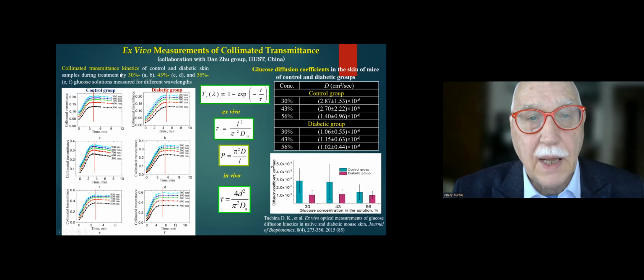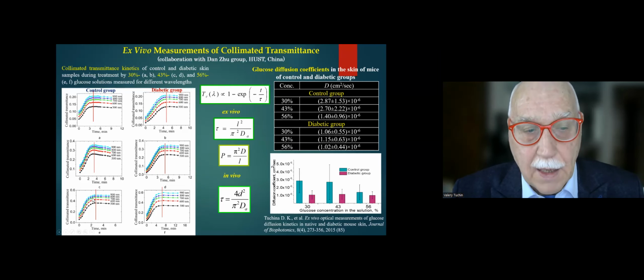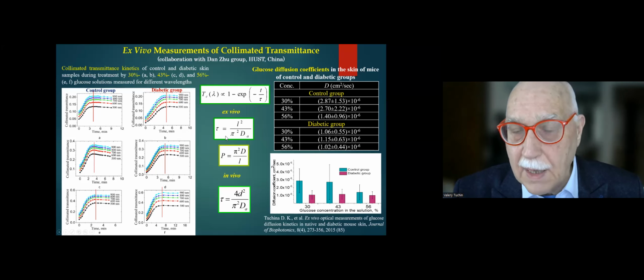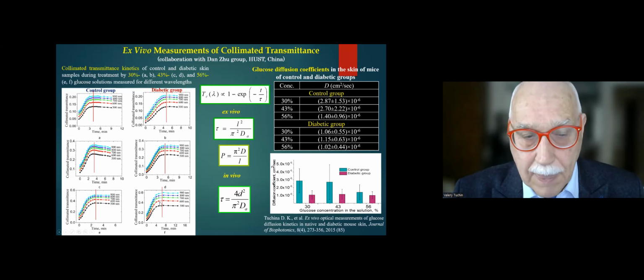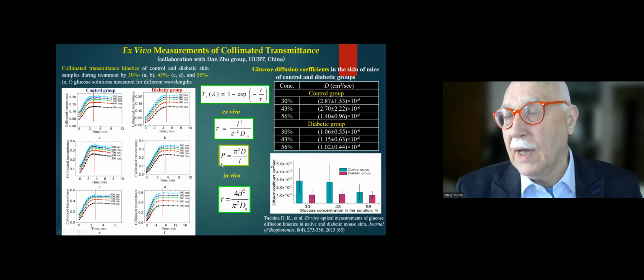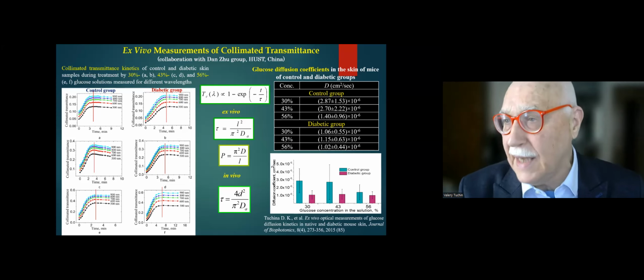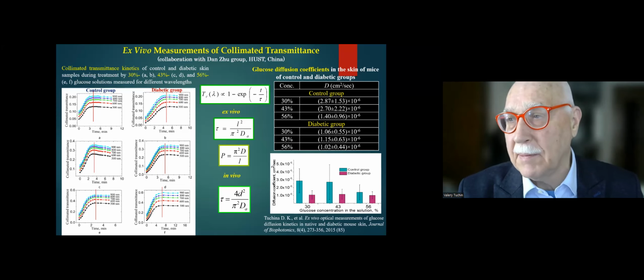glucose. And this is diabetic skin, which was tested. These are samples, it's ex vivo data. This is for the control or normal animals, and this is for the diabetes group. And you see here that we have quite different time of diffusion. It's slightly prolonged for diabetes. And this is due to cross-linking of the collagen due to glycation of collagen within the tissue, and the tissue became more dense and less penetrable for molecules.